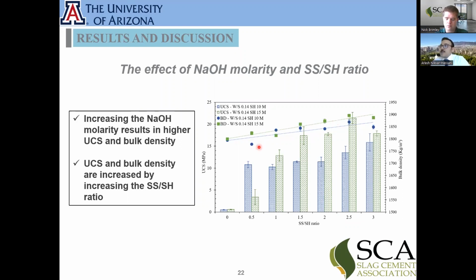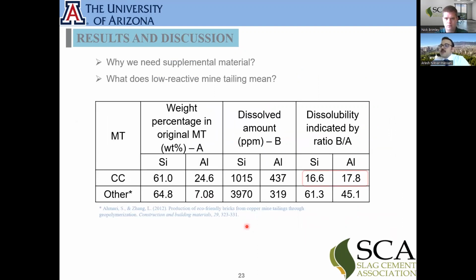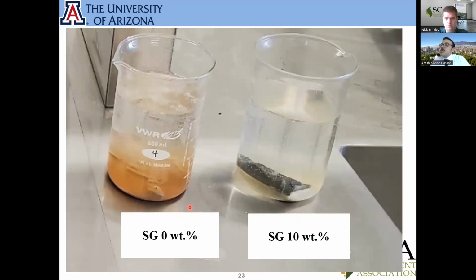But what happens? Are we good now? No, because here we didn't use any slag. This graph shows only mine tailings. And what happened really? I will show you this figure and then we will go back to the chart. Even the maximum UCS sample, when we took it out after the testing and exposed it to the water, the material just decomposed.